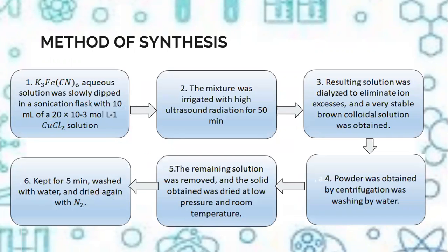Potassium hexacyanoferrate(III) aqueous solution was mixed with the copper chloride solution. After that, the mixture was irradiated with high ultrasound radiation for about 50 minutes. The resulting solution was dialyzed to eliminate excess ions, and it forms a very stable brown colloidal solution.